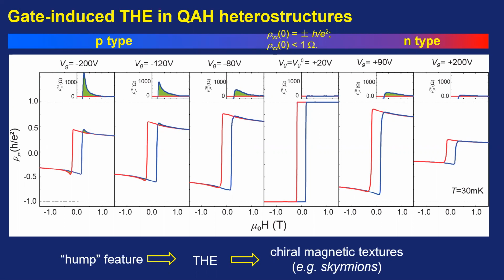Is there any effect of the number of layers of these materials on the quantum anomalous Hall effect? And they qualified that question with one more comment. They said, all over the world now there are only about 5 groups that can realize this kind of quantum anomalous effect, with different groups using different thickness of the sample. The regime I can give you is from 4 quintuple to 15 quintuple. Nobody can realize the quantum anomalous Hall effect with a thickness above 15 quintuple.